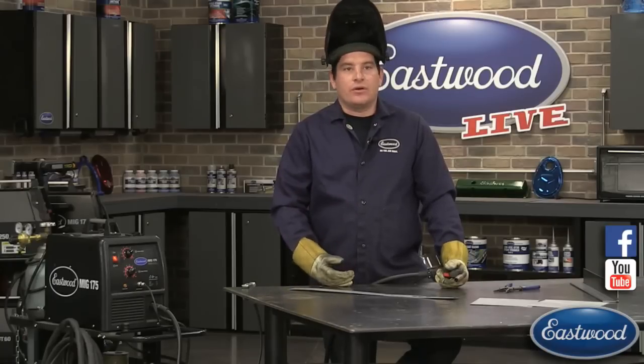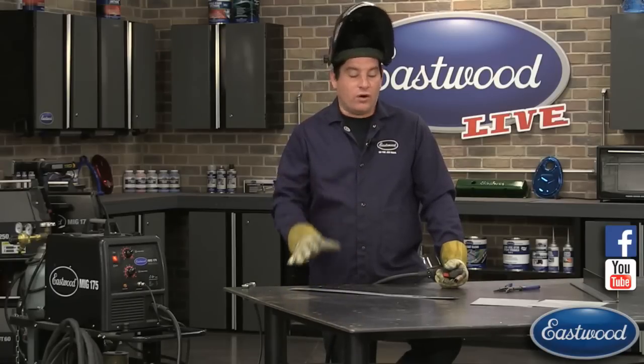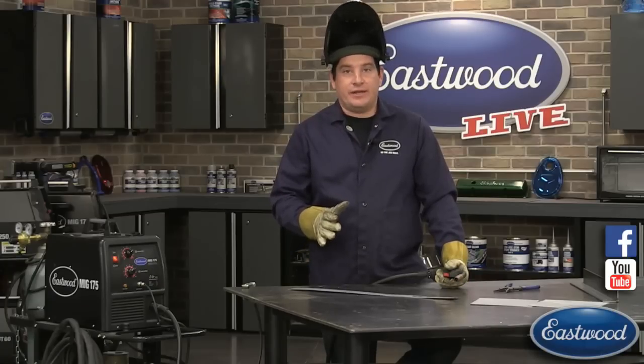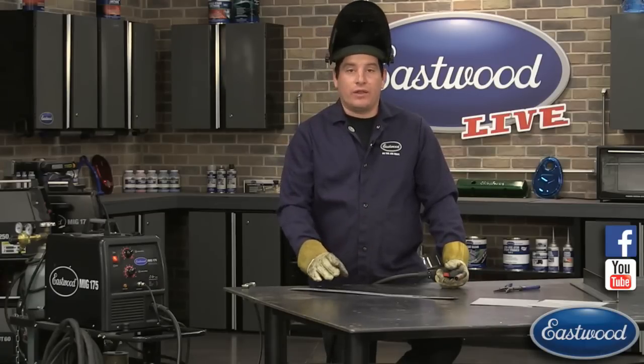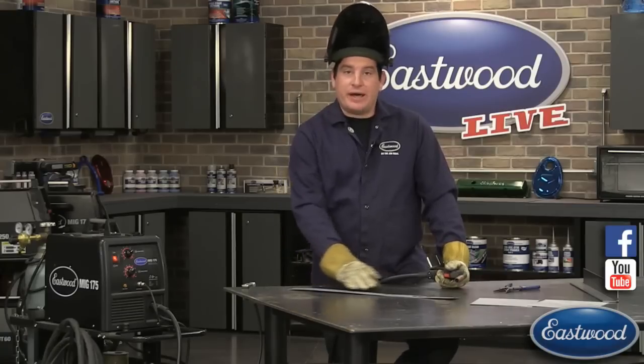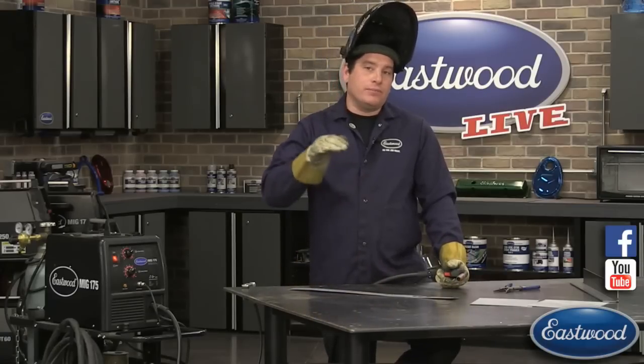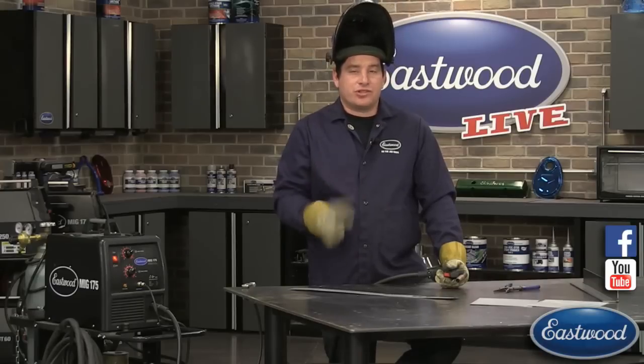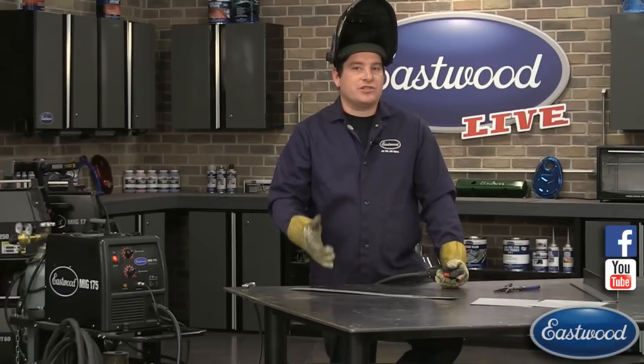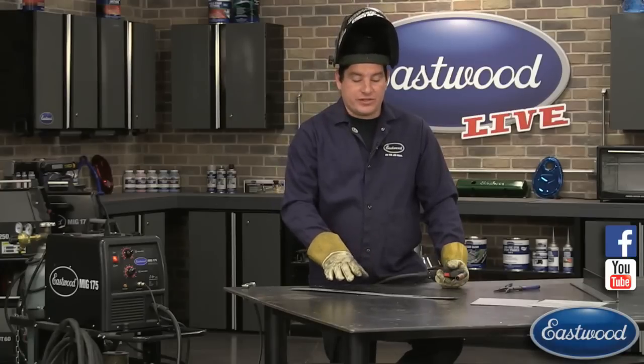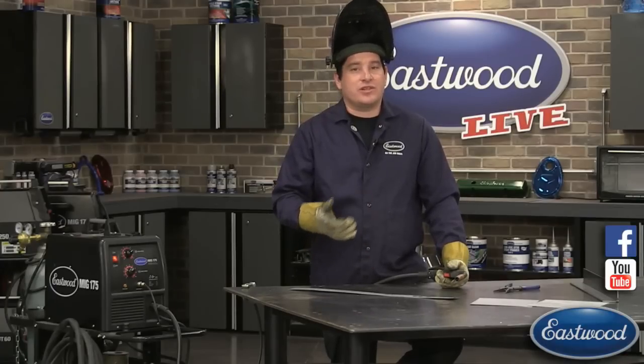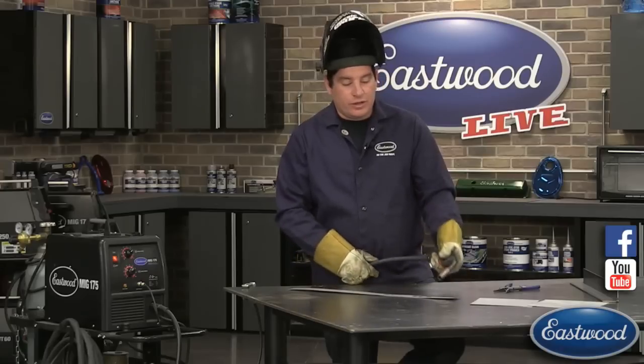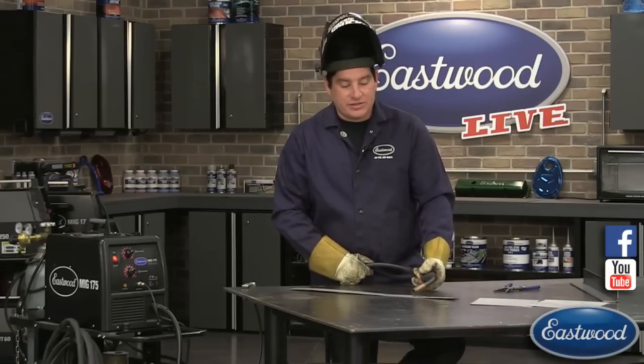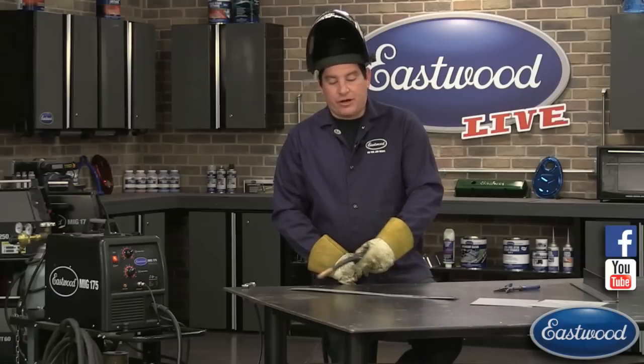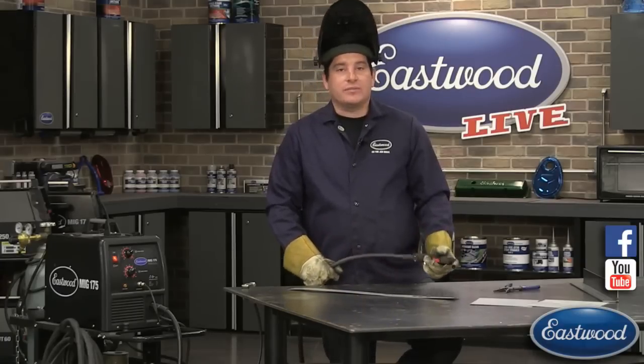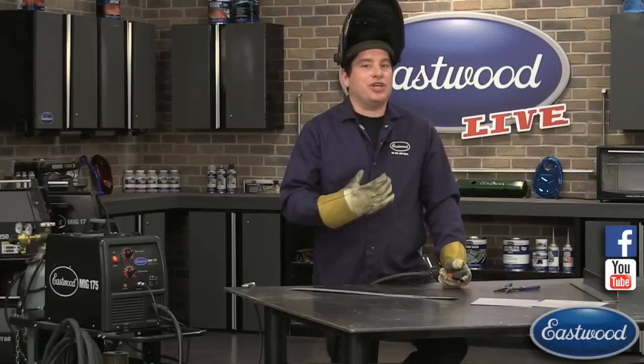Sheet metal is going to warp no matter what. To some degree, it's going to warp when you're doing a butt weld like this on sheet metal. This perfect panel prep tool puts a little bevel on both sides of the panel, which actually puts some strength into these two pieces, which will resist warping a little bit. So it's actually pretty cool. It's going to help the panel from warping, but it's still going to create some warping. It doesn't matter if you weld 3 of these together 3 times in a row and then jump over here and weld 3 times in a row, or if you do 1, it's still going to warp. But what changes it is how much heat you put into the panel.